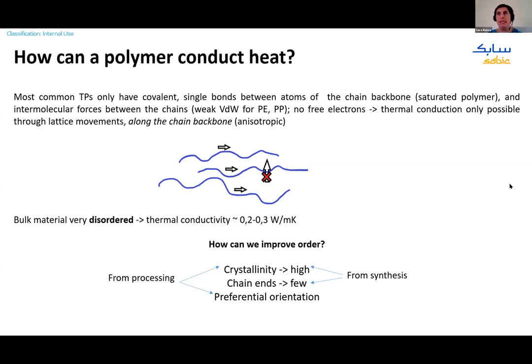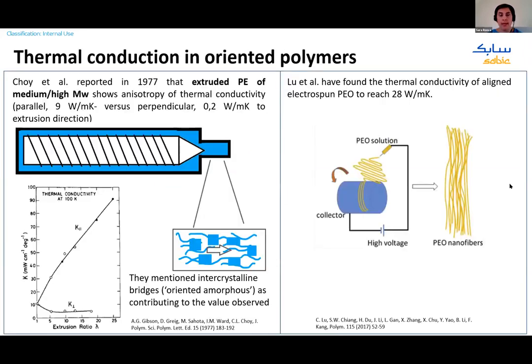The crystallinity, the simplicity of the structure and the number of chain ends are things you can control from the synthesis, the polymerization step. The preferential orientation is something you will control later during the processing, and in turn it will also affect the crystallinity of the material. That orientation in polymers could induce higher thermal conductivity was already proved in 1977 by Choy. He realized that extruded polyethylene of high to medium molecular weight showed anisotropy of thermal conductivity. In the direction of the extrusion, the thermal conductivity reached 9 watt per meter Kelvin, while perpendicular to it was the normal 0.2 value that you would find in bulk materials.